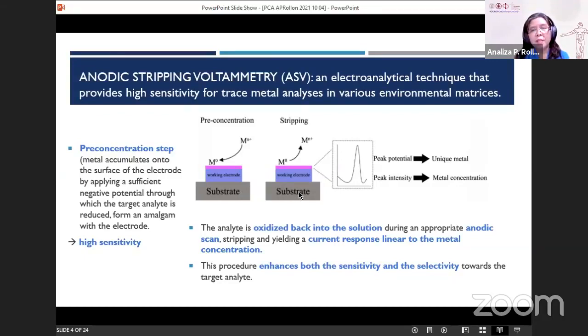And then in the second step, that is the stripping step, the metal is stripped off from the electrode, and that is through applying a stripping potential, and it yields a current response linear to the metal concentration. So which means that if you did the stripping scan, you will see a voltammogram where the peak potential, the potential corresponding to this peak, gives us the identity of the metal, and it should be unique to the metal, and then the intensity or the peak height in terms of the current gives us an indicator of the metal concentration. So this procedure enhances both the sensitivity and selectivity towards the target analyte.